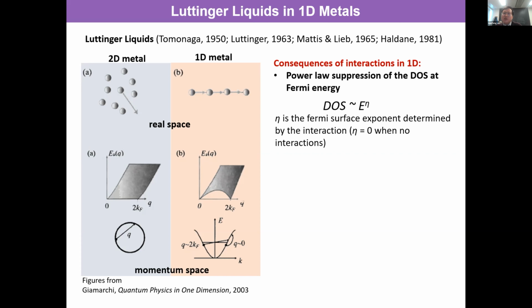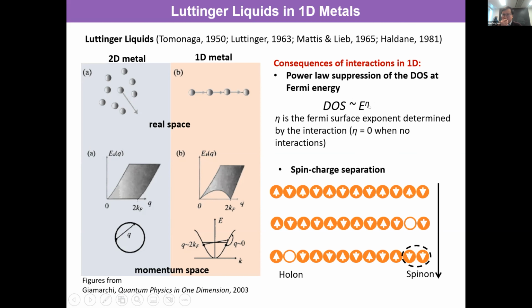So this suppression of density of states at the Fermi surface can be described by a power law, where the density of states is proportional to E to the eta. Here eta is the power law exponent determined by the interaction in the 1D system. Right? So we also know that even though now you can add electrons to the system, you pay some energy, you get an electron into the system, or take an electron out, the electron no longer behaves as a single free electron.